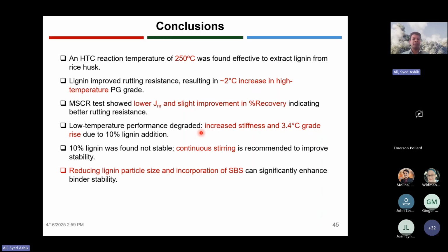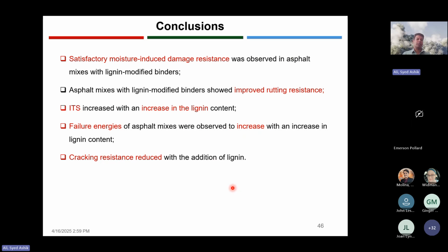But when we go for the 10%, the high amount of lignin, it goes down significantly. 10% lignin was found to be unstable. We may need to do continuous stirring before to improve the stability of 10% lignin. And we have found that the use of SBS modification can significantly improve the stability. So that will be our next target, to see whether we can use this process, addition of SBS, to improve the lignin modification.